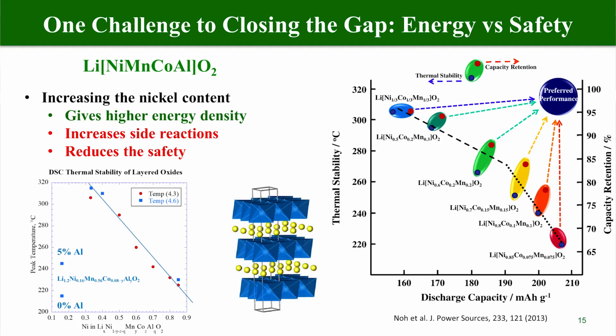If you heat these materials up in TGA, this is where they will lose oxygen. They will lose oxygen at room temperature, given the right catalyst to do it. And this is what tends to give you fires and thermal runaway. But the more nickel you have in there, the higher the energy density. So the goal is to push the nickel content up, push the energy density up, and make them safer. And I'll show you in a moment how we can do that. No one expects these batteries to get this hot, but this temperature scale is a measure of their reactivity with the electrolyte. So the lower the temperature of the evolution, the more reactive they are with these organic solvents.